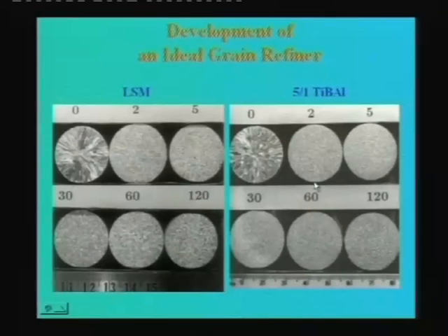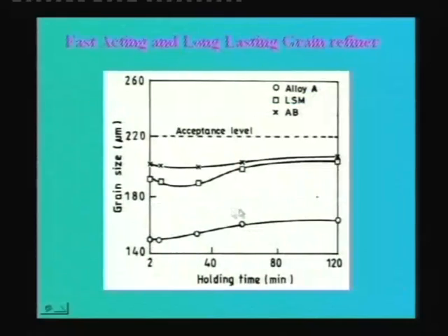This is where we can say that we have been quite successful. This particular technology has already been patented. One company in India has already started making them on a large scale and started selling to Nalco, Balco and Hindalco. So this is a real proven technology which has come out of our department. If you look at the grain sizes, the alloy made here, called alloy A, has much lower grain sizes than either London Scandinavian Metals or Anglo Blackwell.